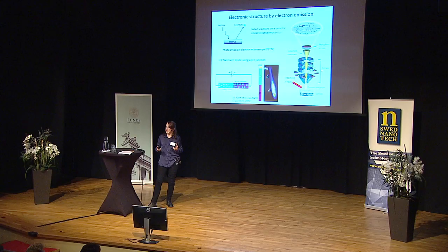What you can do with this photoemission electron microscopy technique is directly image the nanowire, and the very bright region in the center here for the N-type dopant is where you have an excess of electrons. These electrons much more readily come out of the surface. We can really see this immediately with this PEEM technique.